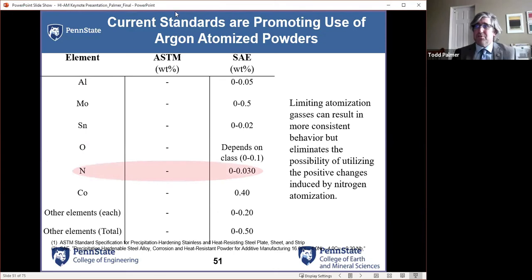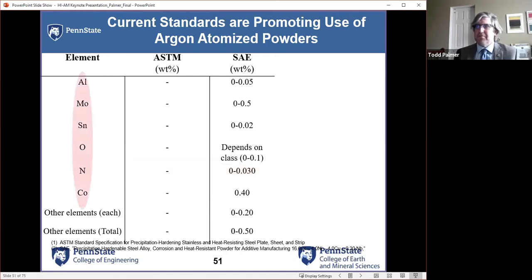but this was one that I wanted to sort of talk about, and I make a big deal of this. SAE International came out with a recent standard, and what they did was they limited the amount of nitrogen. They basically precluded the use of nitrogen atomized powders, even though if we look at it, we can obtain significantly higher strengths. And there's work being done looking at corrosion resistance of some of these nitrogen atomized powders, and they are extremely attractive for a number of ways.